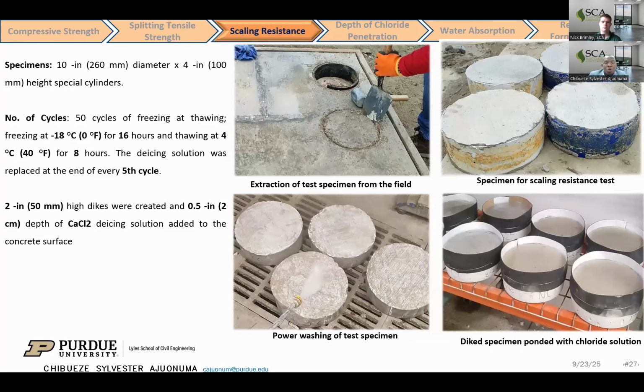Just an overview of the specimens we used for the scaling resistance. The concrete scaling resistance is an experiment designed to evaluate the durability of concrete surfaces. That's the ability to resist scaling when they are subject to cyclic freezing and thawing in the presence of de-icing chemicals, such as sodium chloride or calcium chloride.